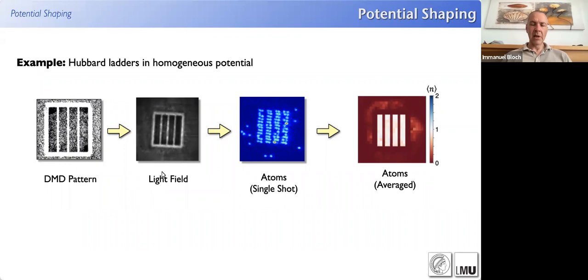Shine a light field off this DMD pattern, and this is the light field we get out of the system. And if we superimpose this light field on top of this optical lattice that you can see, then you can really structure a pattern, the lattice structure, in a way where you now have the two connected wires living here inside these empty regions of light, separated by these boundaries, which are these high potential regions that you can see here. So this allows us to realize so-called quantum ladders, where you have two one-dimensional systems coupled to each other, separated from other two-dimensional systems again.